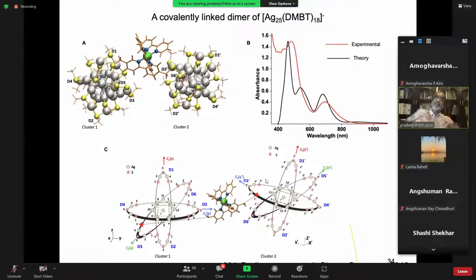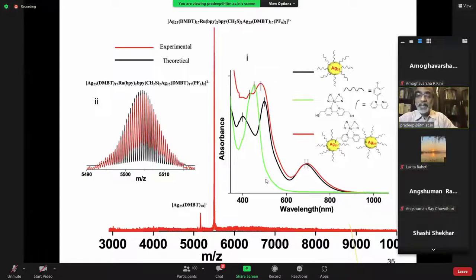Chemistry can be done in solution with appropriate ligands. So here is a cluster, here is another cluster. You can bind it with some dithiol here, and you create a particular kind of reaction where, in specific sites, sulfur or the ligand is exchanged, producing this dimer. Now, we have not been in a position to crystallize it, but the optical absorption spectrum confirms that essentially these features are that of the dimer. You see the dimer as well in the mass spectrum.